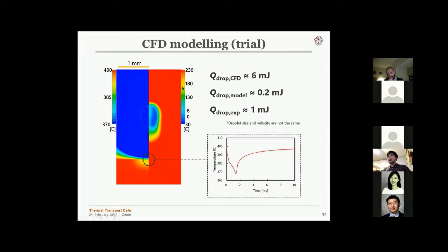And also from this calculation, we estimated the heat taken by the droplet, and we got this value, 6 millijoules per droplet. From the vapor layer model I presented earlier, the heat removed by the droplet is around 0.2 millijoules. And from the experiment, we also obtained a rough estimation of heat transfer by the droplet of around 1 millijoule.